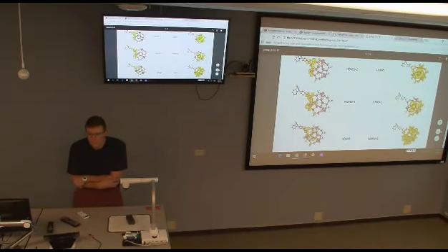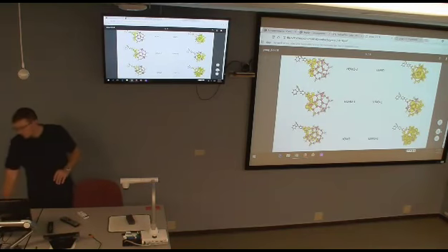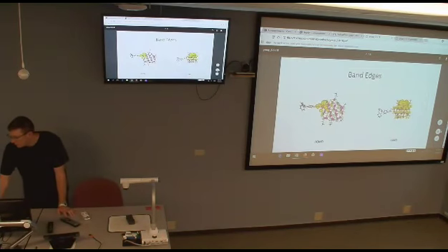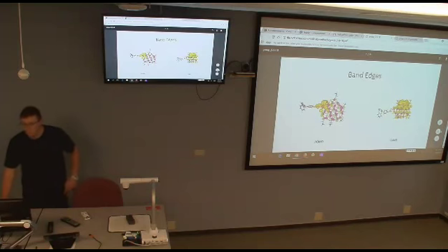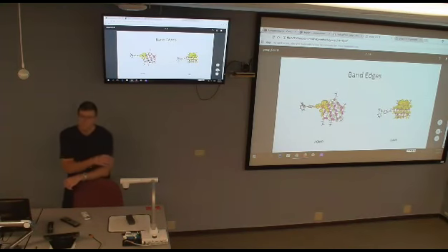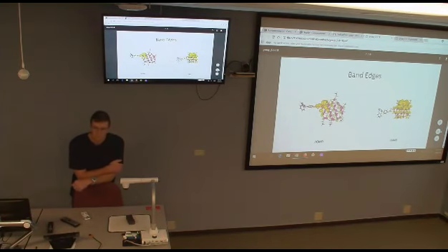But the portion on the molecule and the portion on the linkage is probably questionable, right? Because you look just at the size of bubbles, the more delocalized, the smaller the bubbles, technically, right? And if you have exactly the same ISO value or something, it looks like, maybe I'm wrong, but it's hard to say right now. Maybe you have less contribution on the quantum dot, but you probably have more really on the molecule. So it still will be hybridized, right? But it's just really going more to the molecule.